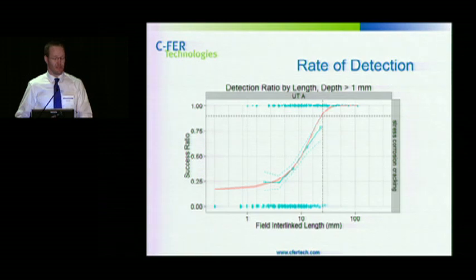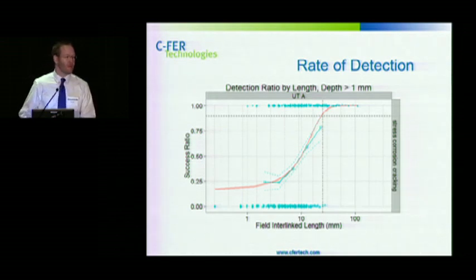There are blue dots along the top. Those represent features that were found by the ILI and subsequently found in the field. And then blue dots along the bottom, which represent features that were missed by the ILI and then found in the field. And what you can see is that as you go from left to right, you get a higher density of the features on the top, meaning that as these features are getting bigger, we're finding more of them.